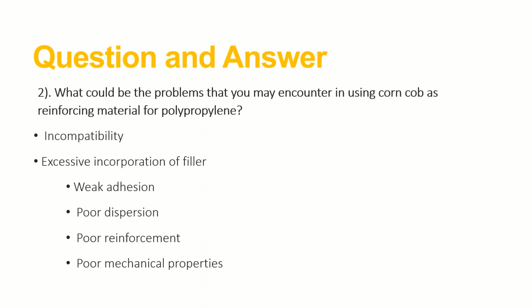While Salma et al. stated that the poor wetting of corncob by the thermoplastic matrix resulted in poor interfacial adhesion between the filler and the polymer matrix as the filler loading increased. Lastly, excessive incorporation of corncob particles may lead to filler agglomeration in the polymer matrix, thus resulting in poor dispersion, adhesion, reinforcement, and mechanical properties of the resulting composite.